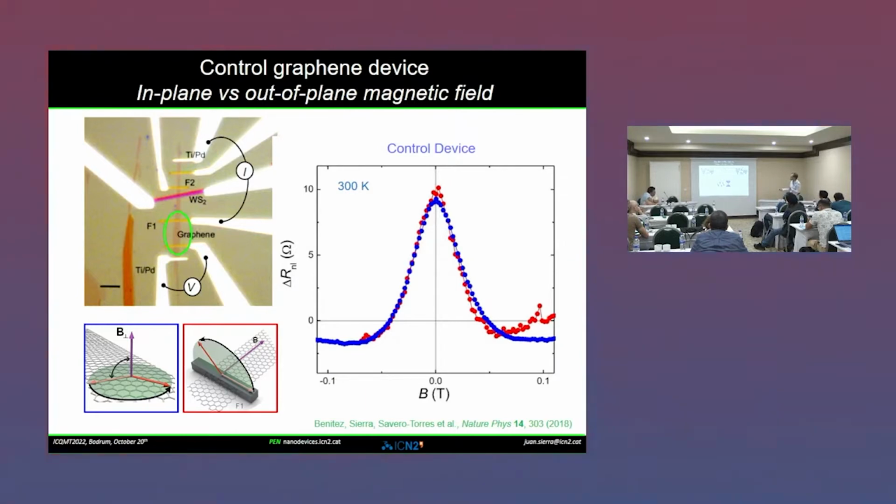And this is because the spin relaxation is driven by Rashba spin-orbit coupling. So in order to observe this strong anisotropic dynamics, you have to introduce inter-valley scattering. In this case, the spins are flipping from one valley to another, and they see different spin-orbit fields when they are in this valley or when they are here. So they have spin-orbit fields in one direction or in another one. So when they are flipping from one valley to another, they are relaxing through the Dyakonov-Perel mechanism.